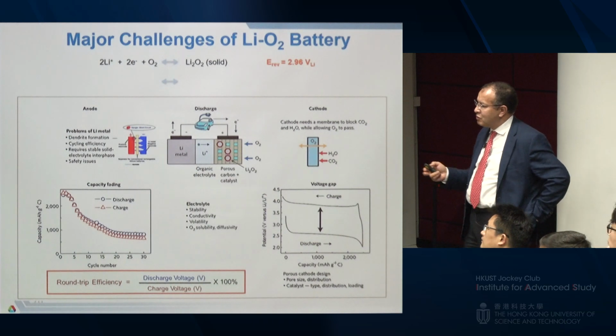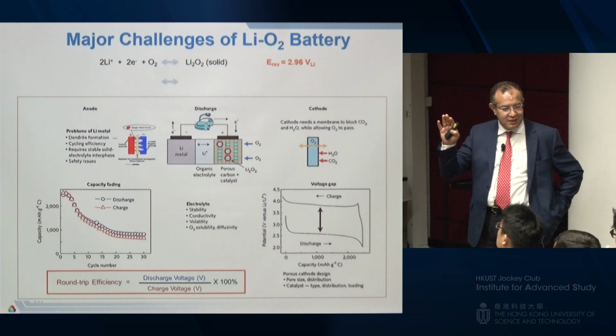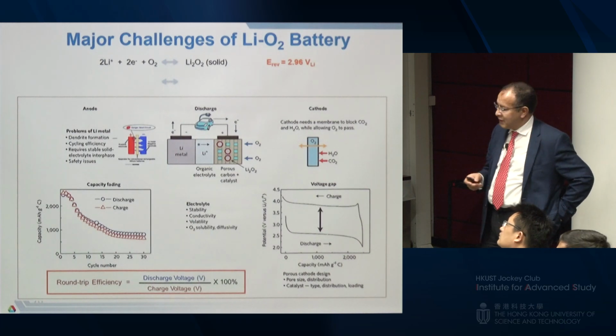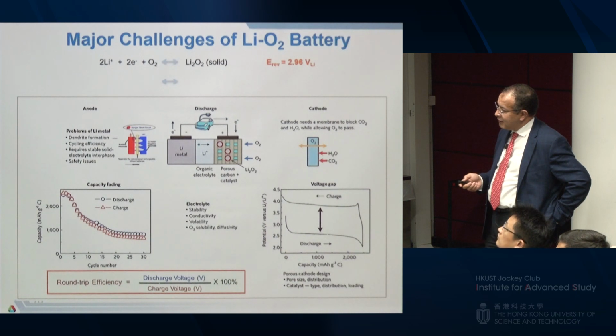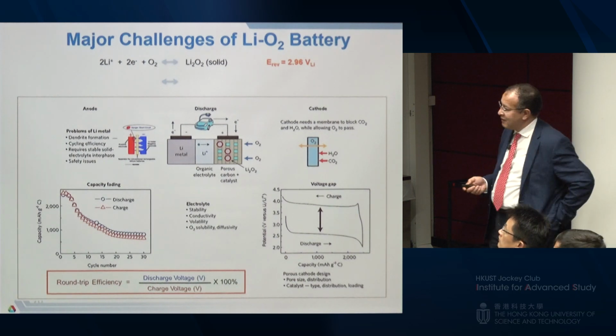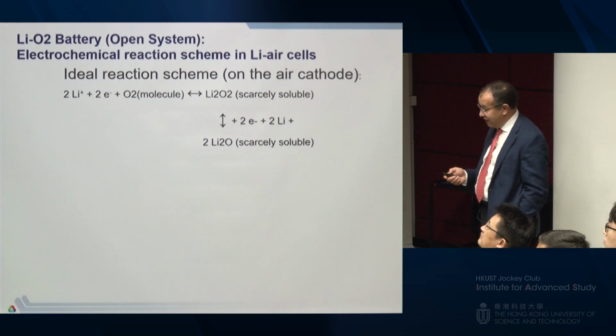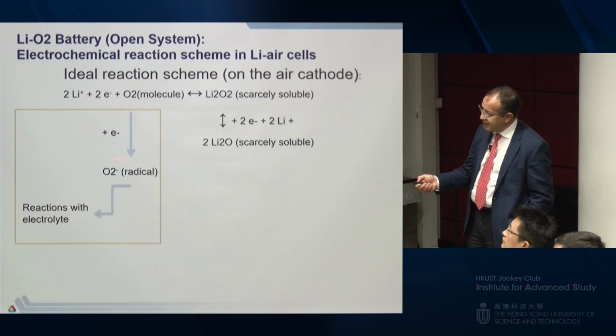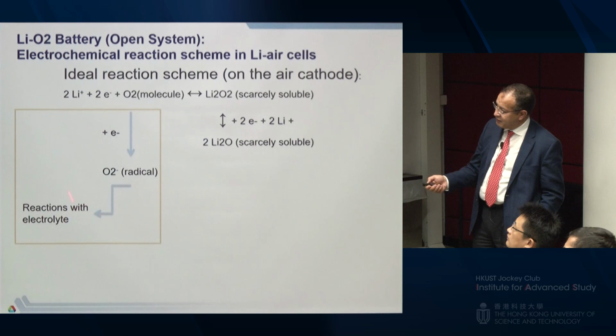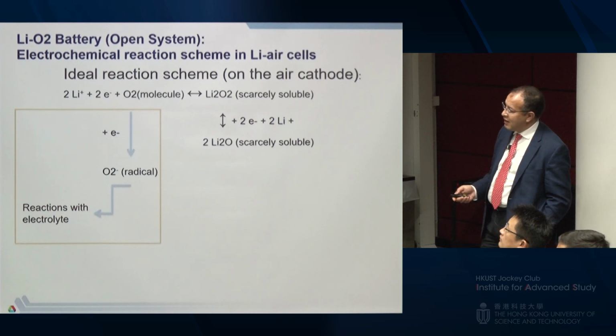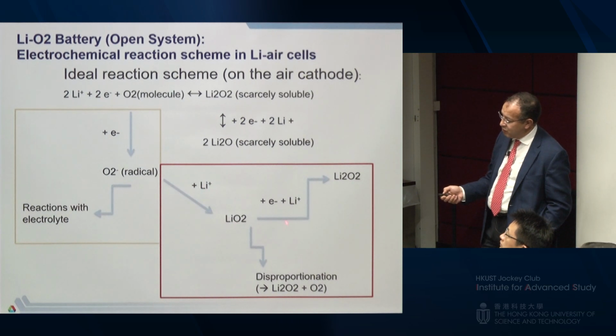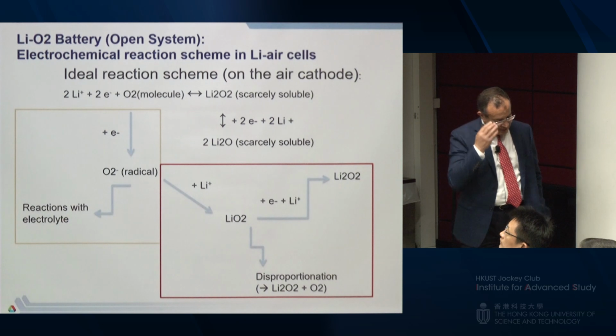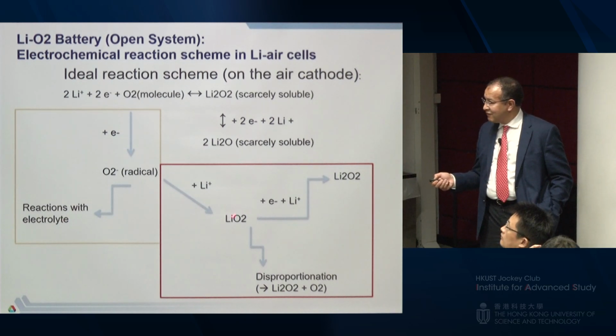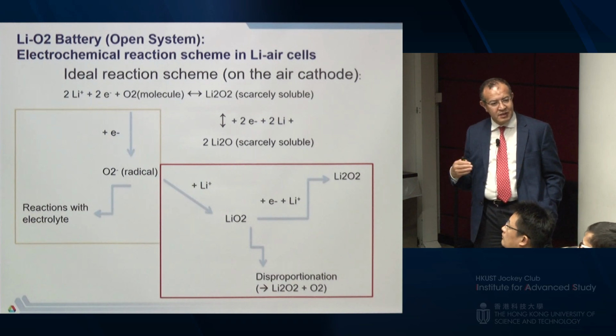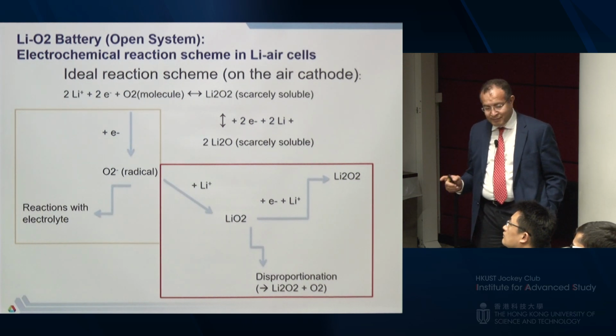So clearly, the good news is there are a lot of people working on it; the papers on lithium air are increasing significantly. There's a lot of interesting things to look at. So I'm going to show you a way to a new system. These are the ideal reactions for lithium air. You can have the first electron transfer to a superoxide radical that can react with the electrolyte, very corrosive. Or if it reacts with lithium, you form a lithium superoxide. Lithium superoxide is interesting because it's conductive, so you can easily dissociate that bond, and it is less corrosive an agent versus peroxide. So if you are able to stabilize this system, you are in good shape.